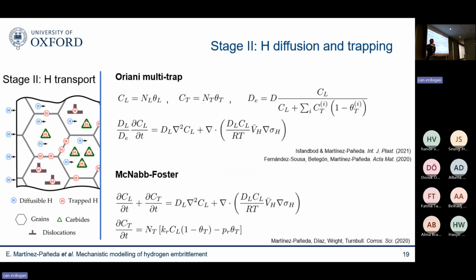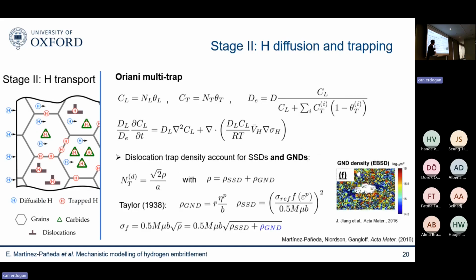The other thing is that hydrogen not only travels freely through the crystal lattice, it's also sequestered or trapped on microstructural defects, grain boundaries, carbides, dislocations. So you need to come up with a theory that's able to encapsulate that, and we work with other people on multi-trap theories based on Oriani or McNabb-Foster, where you basically incorporate the effect of each of those traps through binding energies that quantify how energetically favorable it is for the hydrogen to sit in those places.